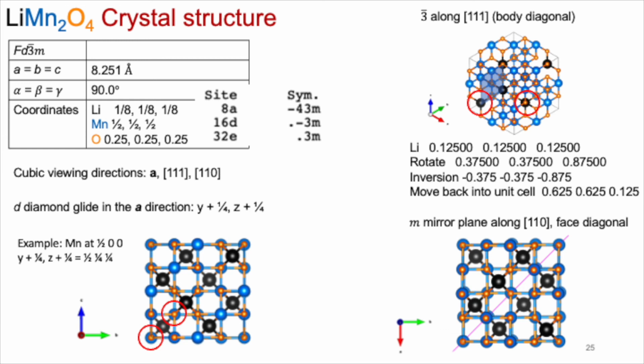Okay, so what about the crystal structure? Well, you think, I see a channel of insertion and deinsertion. That's pretty good. If it's a polycrystalline powder, even though it has anisotropy, the crystals are going to be oriented in whichever direction. So it's going to be sort of a wash, unless you're designing a thin film battery for an Internet of Things application, say for a wearable watch. Then you can orient this crystal and grow it in an oriented direction.